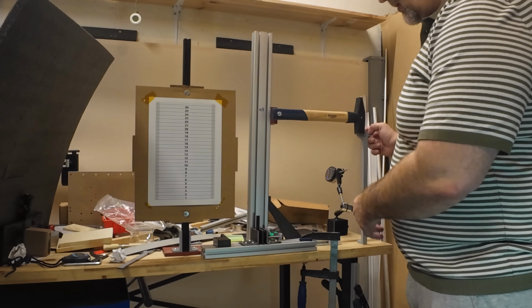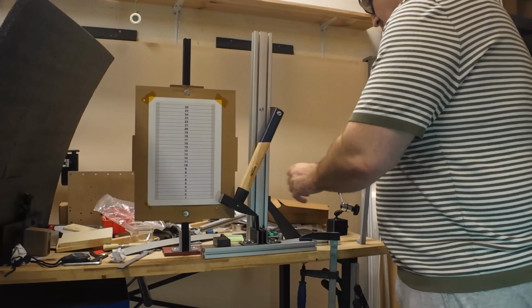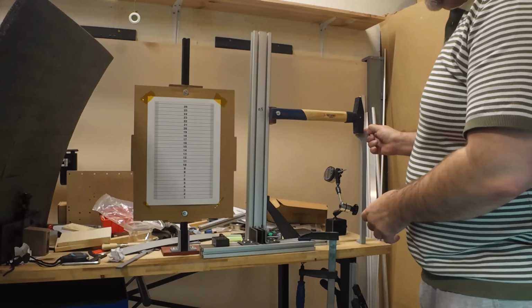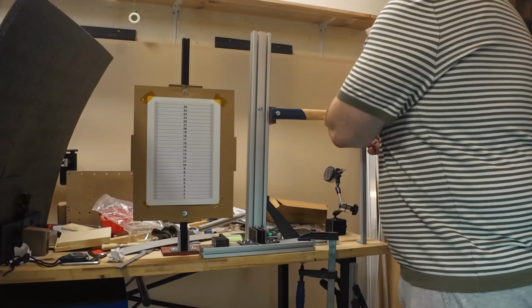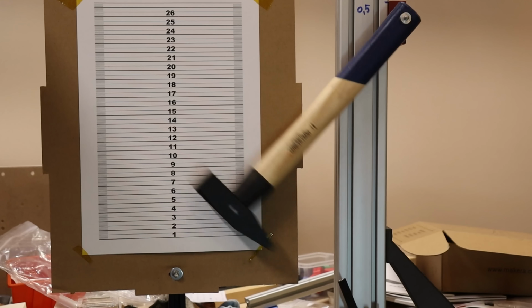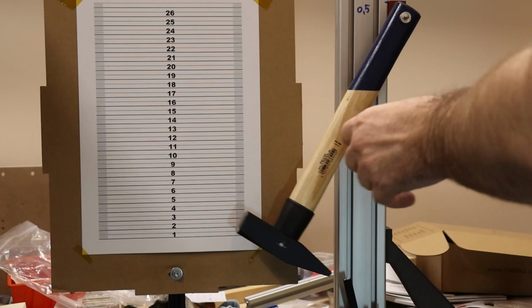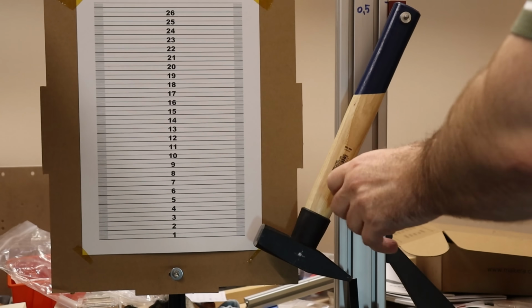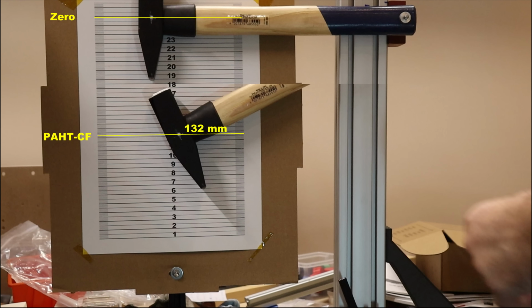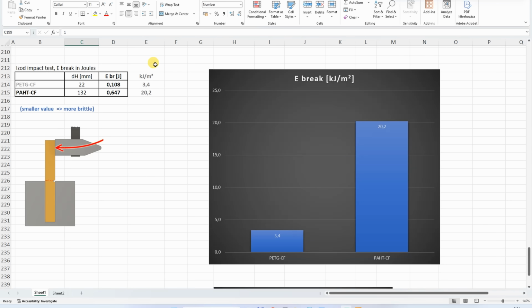Impact test with the half kilogram hammer. 0 position. One more time in slow motion. These are the edge positions of the hammer. 132. I will calculate the breaking energy, but this is tough material. And this is a test where this material shines compared to the PETG or any other material. Even if it is reinforced with carbon fibers, this is quite tough material.